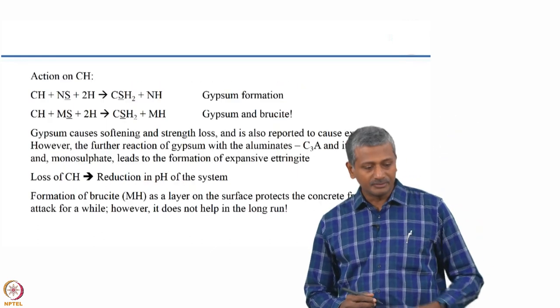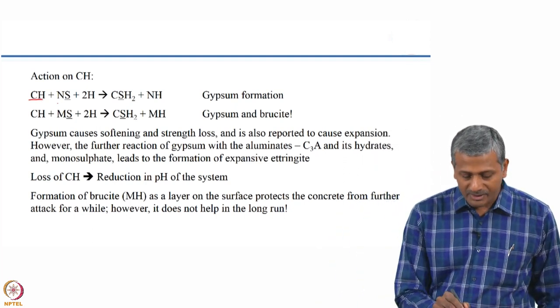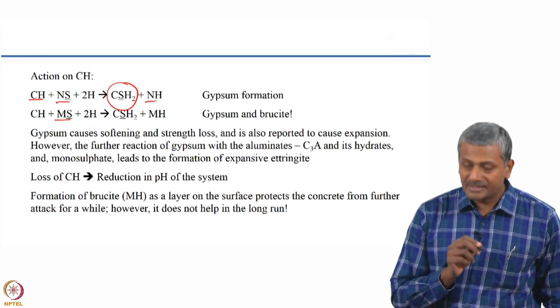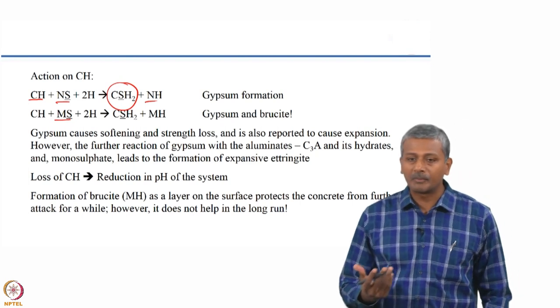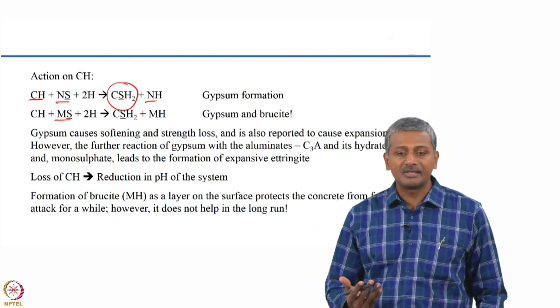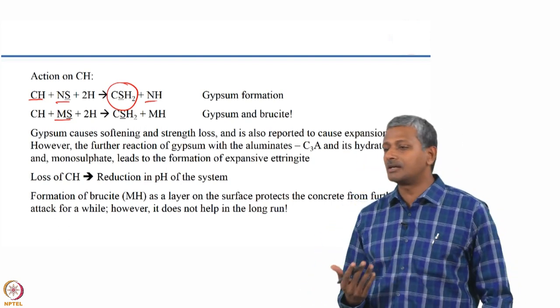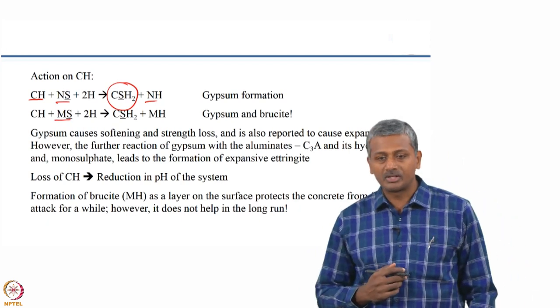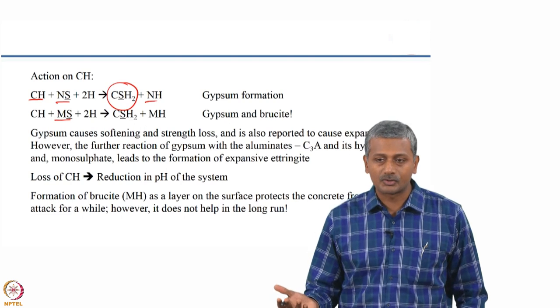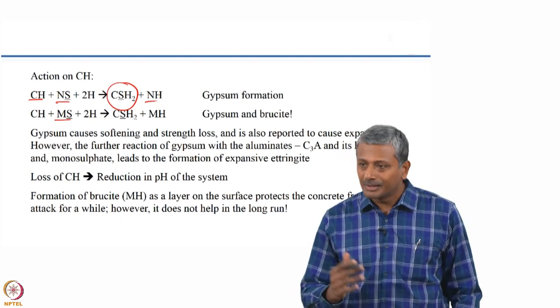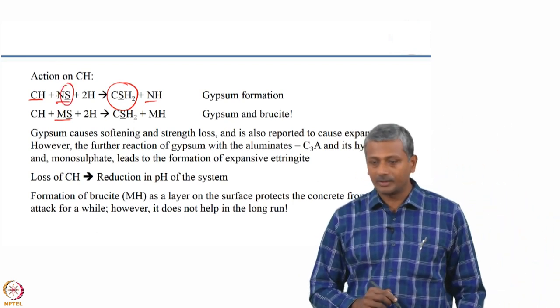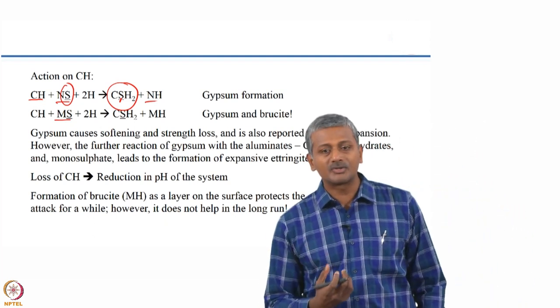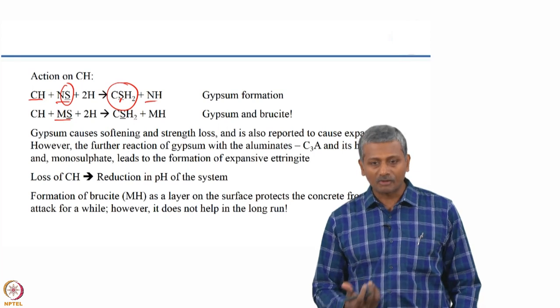In simple terms, the reaction between calcium hydroxide and sodium sulphate leads to the formation of gypsum and sodium hydroxide. If you have magnesium sulphate as the attacking solution — and note that sodium and magnesium sulphates are well studied because they are highly soluble and accelerate the process significantly in a laboratory environment — the sulphate first reacts with calcium hydroxide to produce gypsum. Gypsum itself is not a very hard material, so you are transforming calcium hydroxide into something softer, causing some softening and strength loss. There is also literature suggesting gypsum formation causes expansion at very high sulphate concentrations, though there is some controversy regarding that.